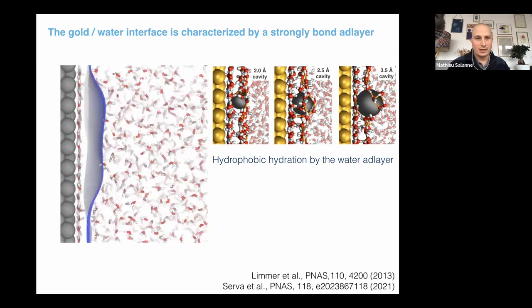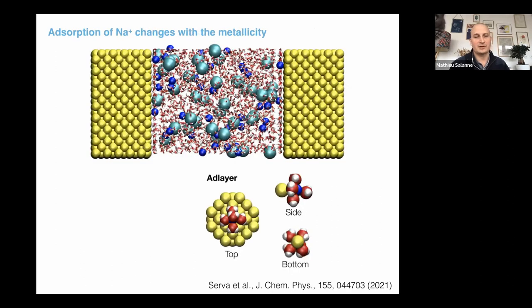So we came back to the system, and we tried to see what was the effect of the metallicity. And again, we simulated a very simple system, so sodium chloride in contact with gold. And so with previous parameters, so the ones that were used a long time ago by Michiel and then never changed by us or anybody else, we had this kind of picture. So all the ions, sodium and chloride, tend to adsorb in between the first adsorbed layer of water and the second layer. So they go, in fact, in this kind of liquid vapor cavities that were highlighted in the previous slide.